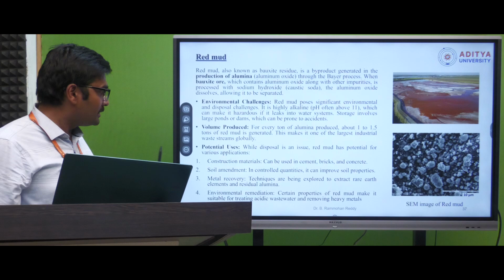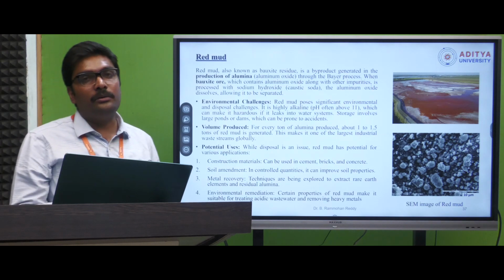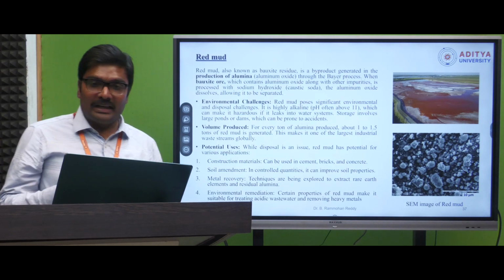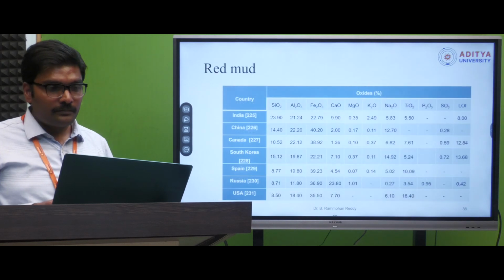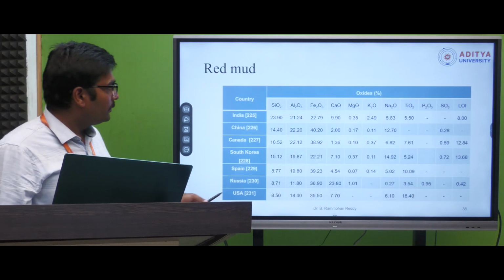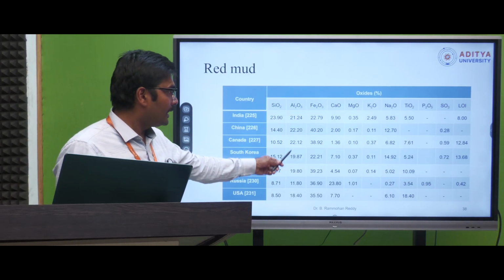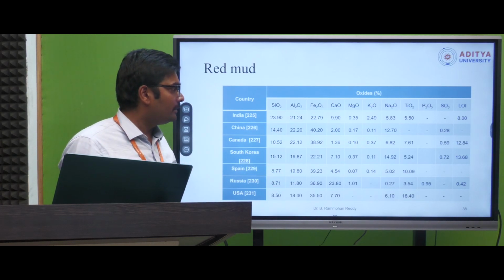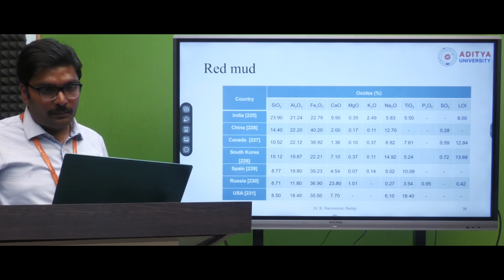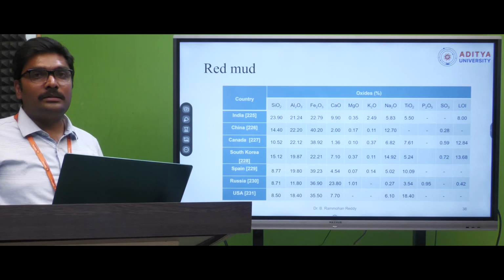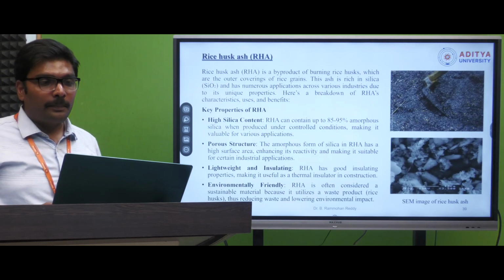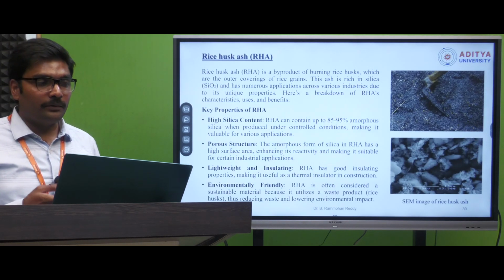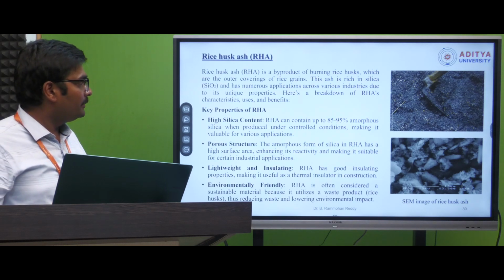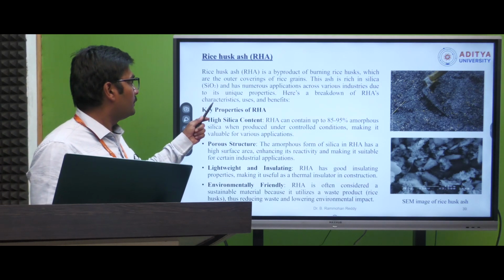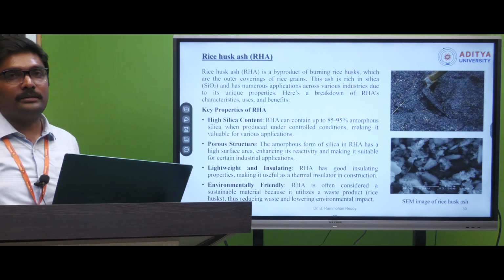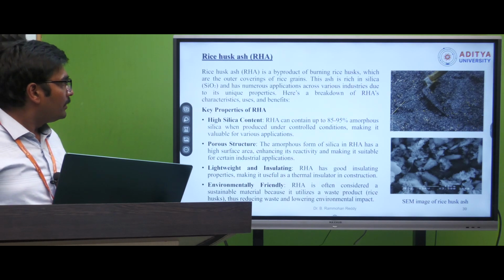If you use it in construction, that means in the production of concrete, it will give better properties. And in the chemical composition, the silica content, alumina content, iron content and calcium content are also good in the red mud, so that we can use it as a pozzolanic material or a binding material in the production of geopolymer concrete.